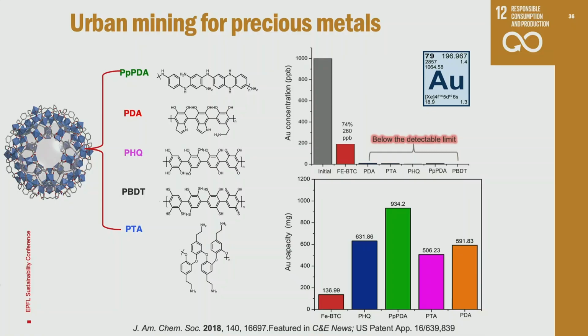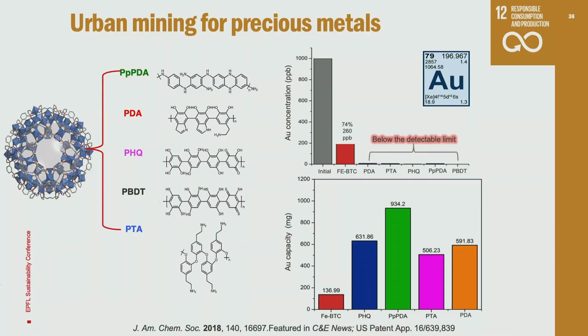So we began to design materials specifically for gold. The student made this MOF, same one. We just varied the polymers inside. And what we found is that when we took these materials, here you can see the gold concentration. When we treat it with the MOF, it drops quite a lot, 74%. But when we treat it with the MOF polymer composites, we basically are getting below our detectable limits, which is, for some of you who know, in the ppb regime, which is very low.